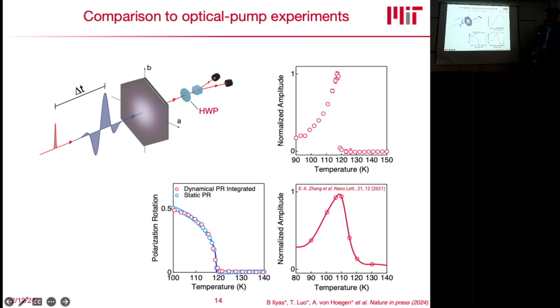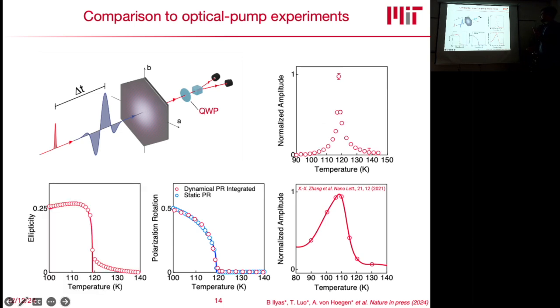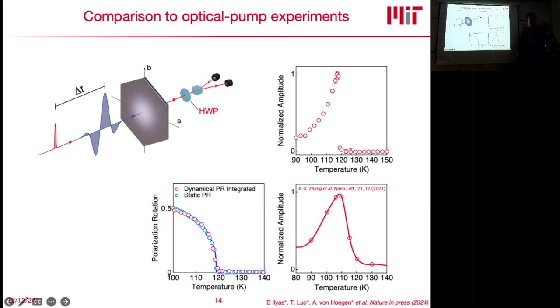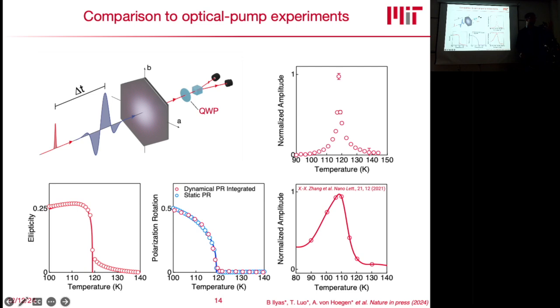So what we found is that if you integrate this over temperature, you get perfect agreement with the static measurements. And this was very discouraging, because we thought, okay, we're doing something non-thermal here with our terahertz excitation, but it also seems like it's just increasing the temperature. What was a little bit more encouraging is that if you now replace your half wave plate with a quarter wave plate, so instead of measuring the polarization rotation, you measure the ellipticity, the temperature dependence looks dramatically different.